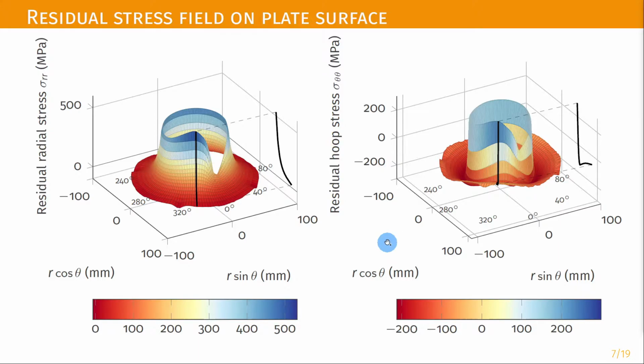It is worth noting that the values of stress, especially the radial one, are significant, with a value around 500 megapascal close to the weld toe. This is because of the simplifying assumption of a null radius for the weld root and weld toe. The magnitude of residual stresses produced is quite considerable in this case. They indeed reach values around the yield strength of the material.